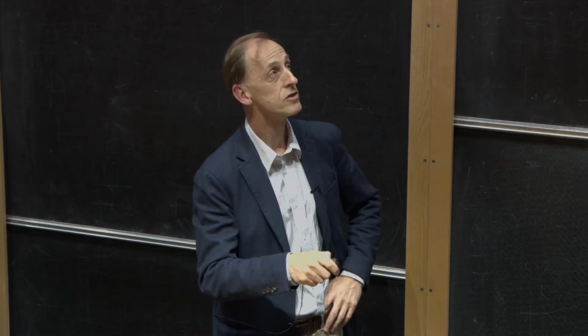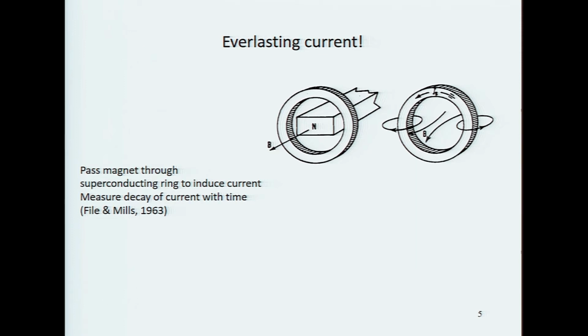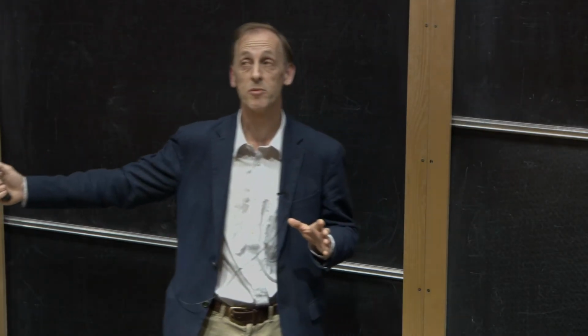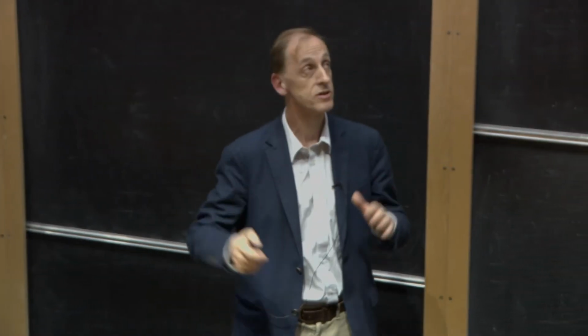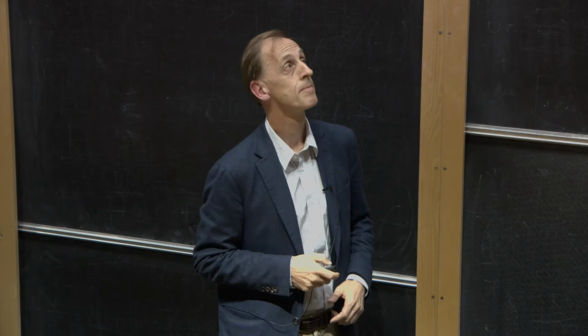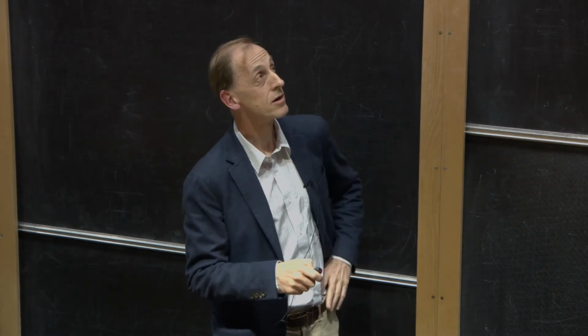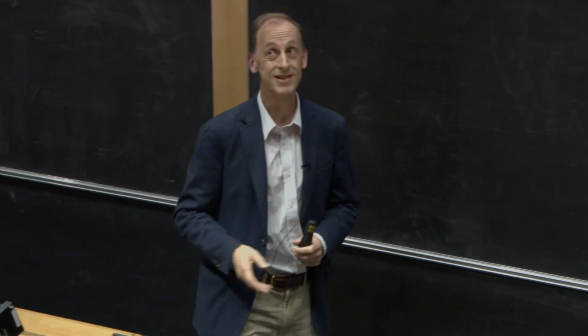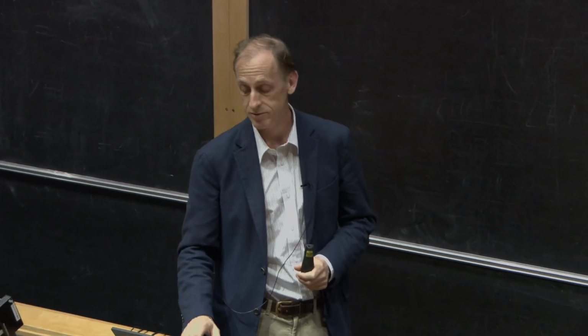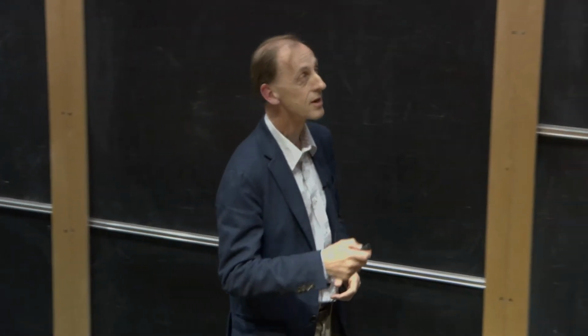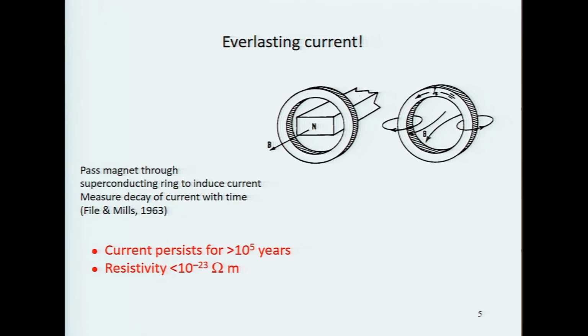So after the current had been induced, the current has associated with it a magnetic field, and what File and Mills did was they measured this magnetic field strength as a function of time, and in fact they continued the experiment for several months and continued measuring this magnetic field strength as it decayed over time. And it in fact decayed extremely slowly. So slowly, in fact, that they couldn't really detect a reduction in the current over a time scale of several months. And the conclusion from their work was that the current in this loop would persist for 100,000 years if they let it continue going for that long, which, of course, is not very practical.